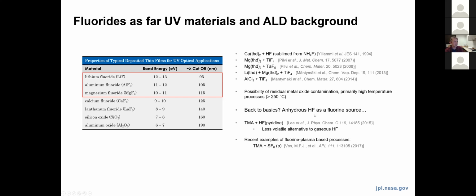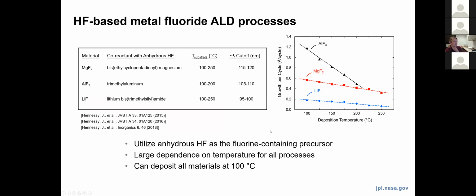And I'll describe some of those results in the next few slides, but basically this is a simple way to get a reactive ALD process that can work at low temperature and that can yield a metal fluoride film that has low contamination and therefore low loss. Of course, for those that are familiar with semiconductor processing and have been in a clean room, HF is a fairly nasty chemical, so there are handling concerns, admittedly, to using this process, but with appropriate controls, we've had fairly good success at depositing these materials. So again, using this HF route, we've developed ALD processes for all the metal fluoride materials that we're interested in, and maybe more importantly, for some of these mirror coating applications, we can deposit them at relatively low substrate temperatures. So again, materials like aluminum fluoride, magnesium fluoride, and lithium fluoride.